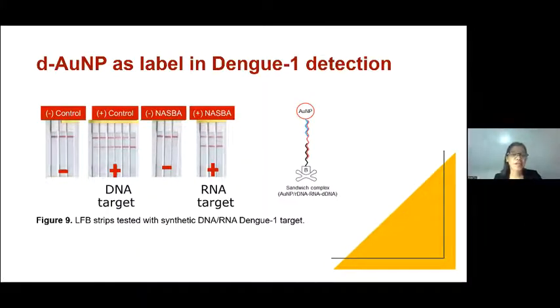The 10 nanometer D gold nanoparticles functionalized with DNA were successfully used as label in a lateral flow biosensor for the detection of dengue 1. Figure 9 shows some LFB strips tested with the target. As you can see, the negative control gives 1 line, which means negative in the LFB test. The positive control using synthetic DNA and RNA targets produces 2 lines, which means positive in the LFB test.